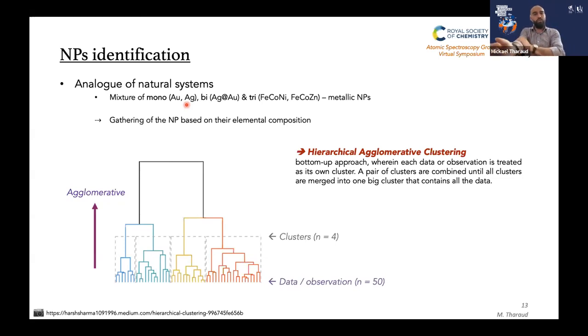So we decided to go for hierarchical agglomerative clustering, which is a methodology that starts from the bottom, saying that each observation, and in our case each nanoparticle, is its own cluster. And then it iteratively agglomerates the observations one by one based on their similarities. Here, for instance, we started with 50 observations and finally ended up with four different clusters. So in theory, it's pretty interesting and very easy.